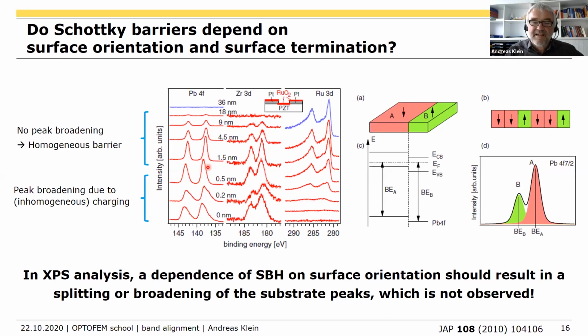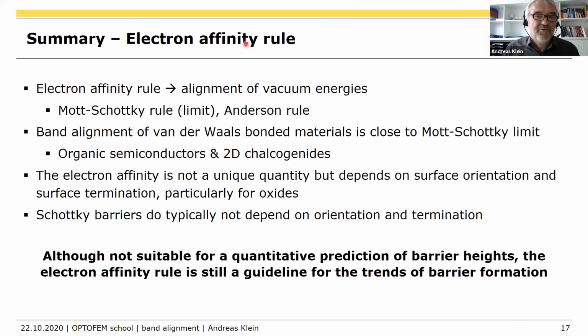And because this is a polycrystalline sample, which exposes, in principle, any surface orientation, and that's also a ferroelectric material, we also have different polarizations. So whatever you do, the Schottky barrier is the same. This is also from the other experiments we have: in most cases, we do not observe a dependence on surface orientation or surface termination. So that means this electron affinity rule still gives us a good guideline for predicting if you get a high or a low Schottky barrier.